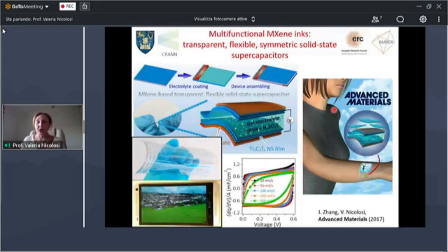So what have we done in the last few years with these materials? So this is one of the earliest works with MXenes. We managed to actually build a very large area, transparent, flexible, symmetric solid-state capacitors. These materials are beautifully conductive, mechanically very, very stable. So what we see here is a fully assembled supercapacitor device for energy storage, where you have both electrodes, you have 2 electrodes and the gel electrolyte.